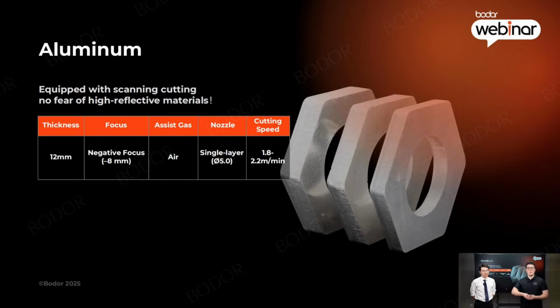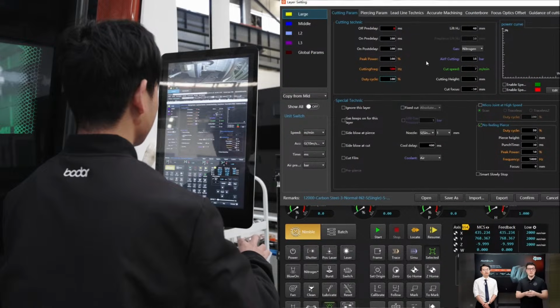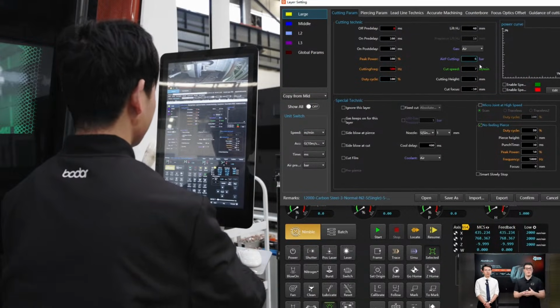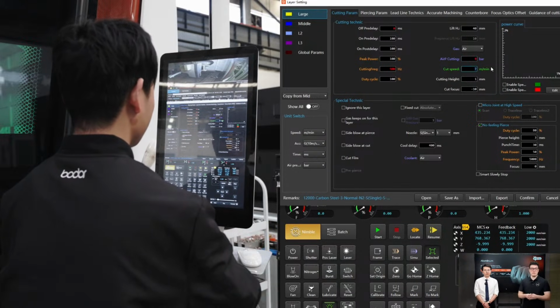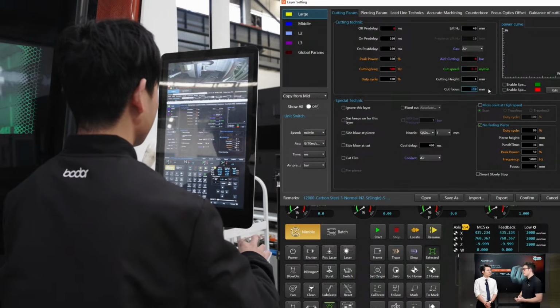Aluminum. Aluminum looks beautiful when it's done right, but as you probably know, it's also one of the trickiest materials to cut. We are working with a 12 millimeter aluminum sheet, and for this demonstration, we are using a 6 kilowatt C-series machine equipped with a scan cut laser head, a single layer nozzle of about 5 millimeters in diameter, a negative focus of roughly -8 millimeters, and air as the assist gas.